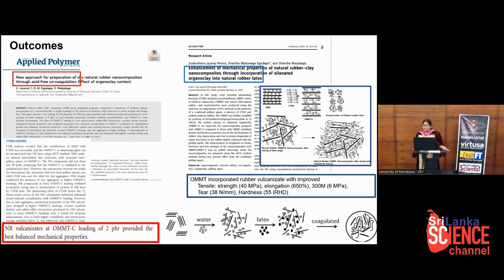The outcome of my research: we found a new method to produce nanoclay composites starting from natural rubber latex, and it was successful. The clay is first made into a dispersion form, and this aqueous dispersion is incorporated into liquid latex, and then the clay exfoliated structures are formed. The liquid nanocomposite is then dried or coagulated in situ, so the clay is dried as well as the rubber becoming a dry form.